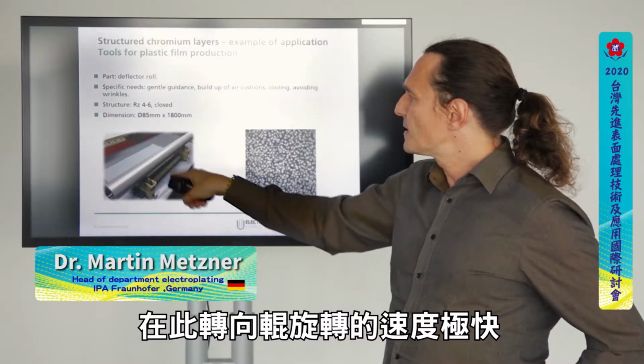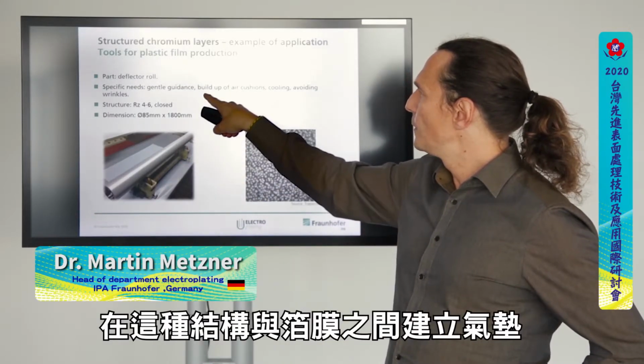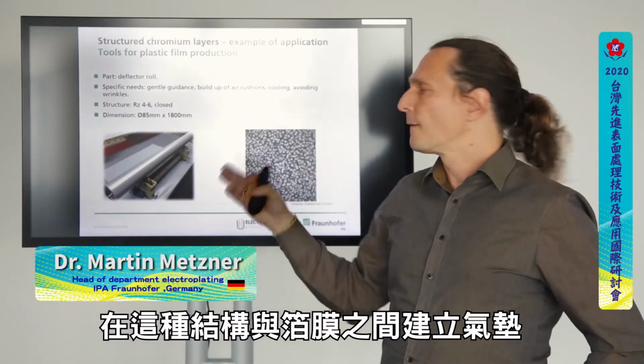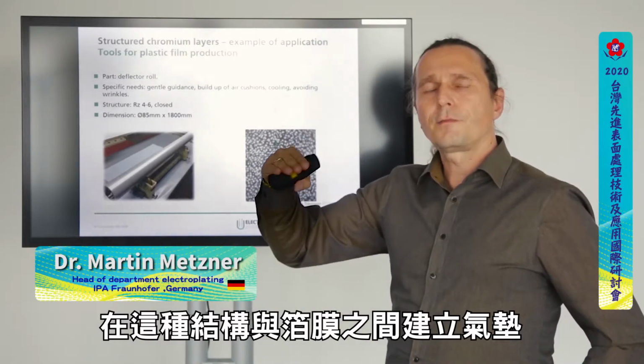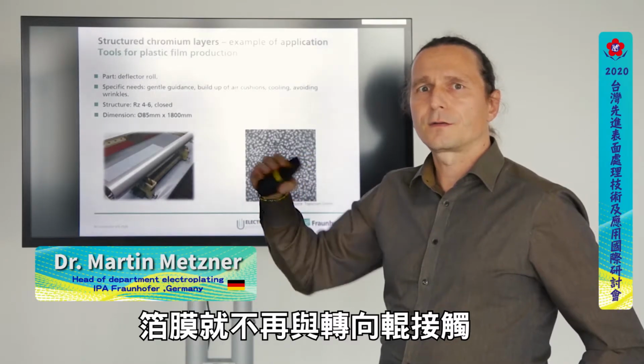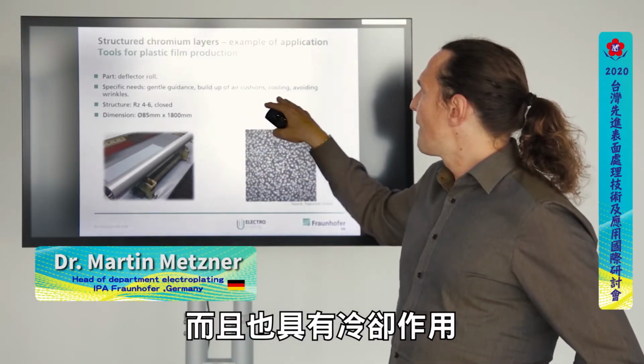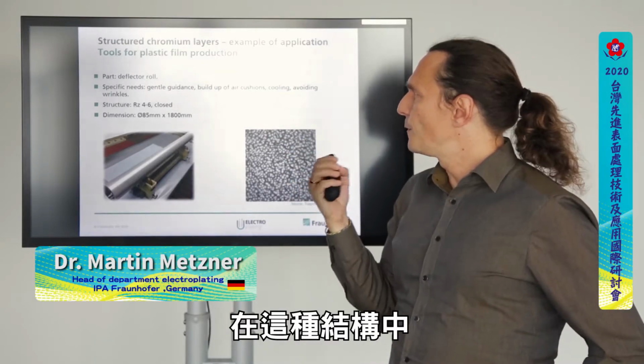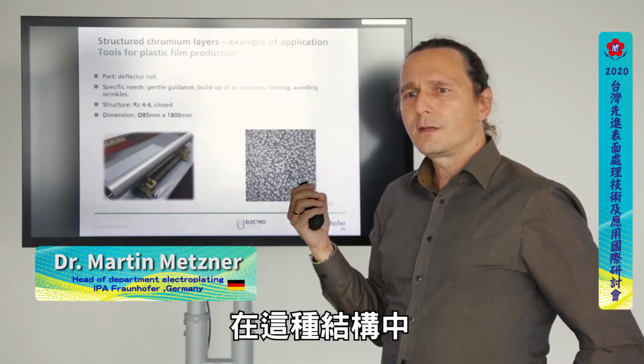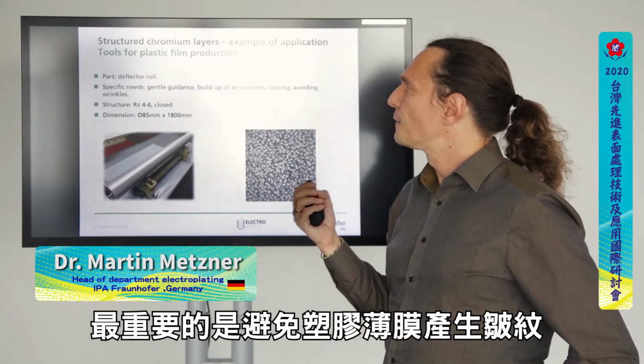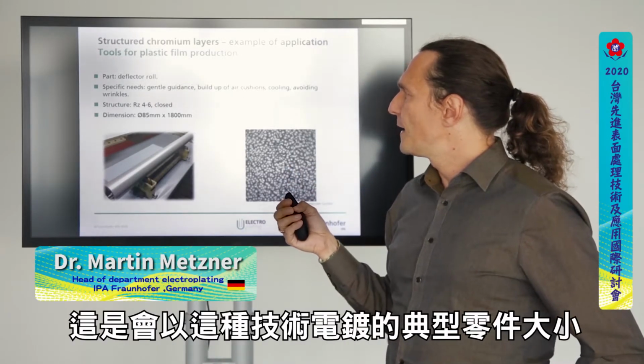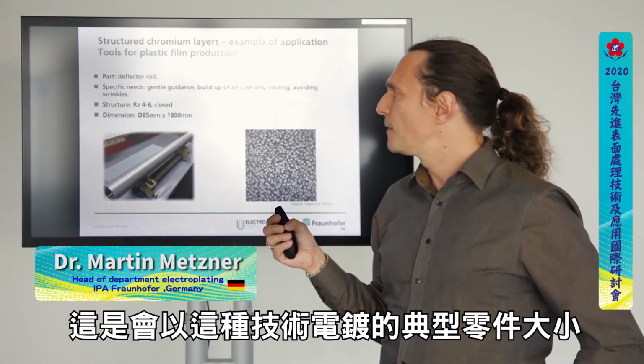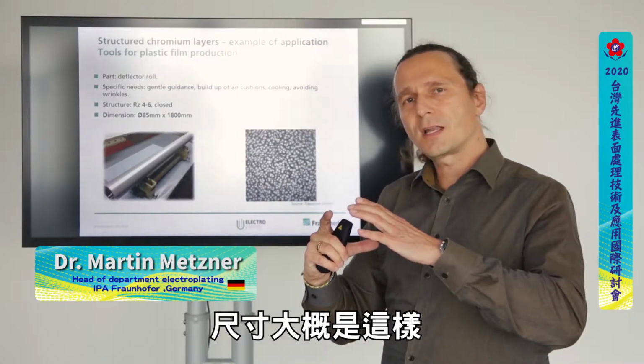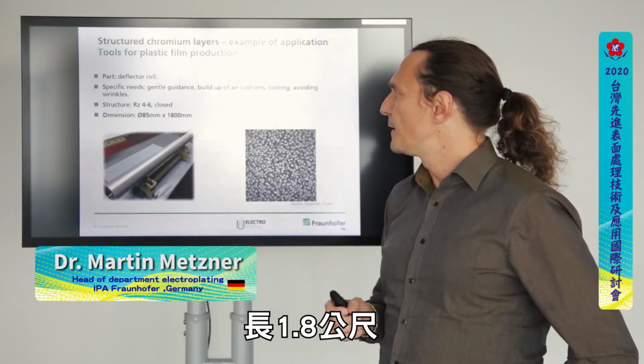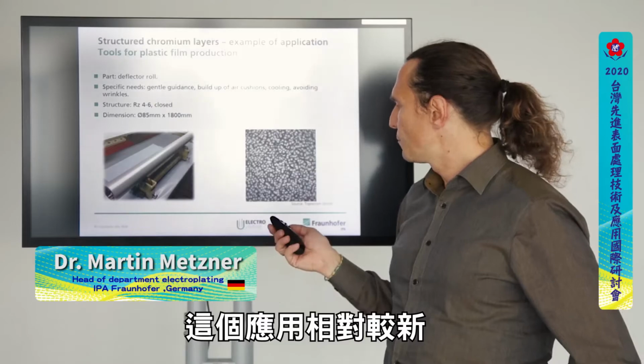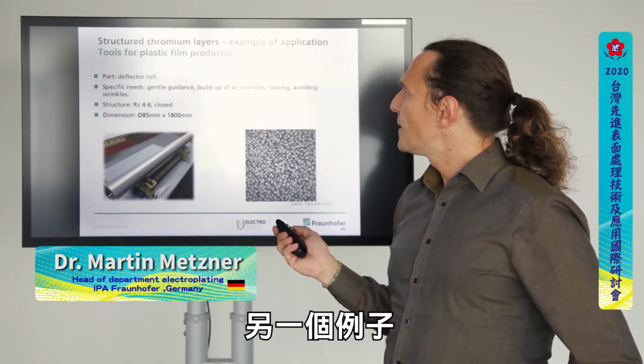The mechanism here is that this roll is spinning around very fast and we build up a kind of air cushion between this structure and the foil. So the foil does not really have contact to this roll anymore. And you see here, it's also a cooling effect, and what's very important in this structure is to avoid any kind of wrinkles in this plastic film. And you see here again the typical size of parts that are plated with this technology, dimensions like that, 1 meter and 80 centimeters long. This is a relatively new application now.